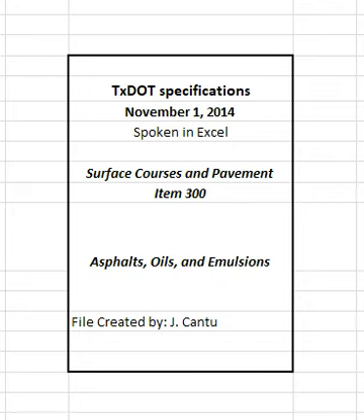3. Exception to T49, substitute the cone specified in D217 for the penetration needle. 4. Allow no crack in the crack sealing materials or break in the bond between the sealer and the mortar blocks over 1/4 inches deep for any specimen after completion of the test. 2.9 Asphalt rubber binders. Provide asphalt rubber, AR, binders that are mixtures of asphalt binder and CRM, which have been reacted at elevated temperatures. Provide AR binders meeting D6114 and containing a minimum of 15% CRM by weight.